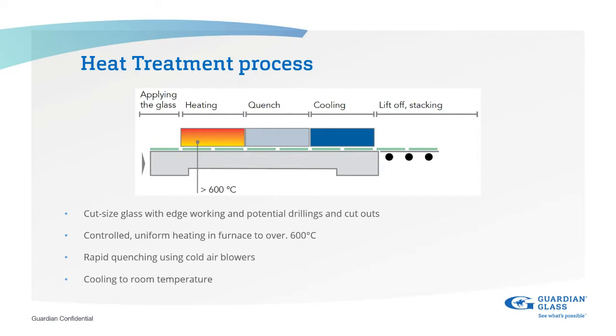Now, as you can imagine, when the glass reaches its temperature of around 630 degrees, it starts to become soft. Once the glass is up to full temperature, it will move into the quench section and the cooling section. As you can see on this drawing, we have a quench section and a cooling section. Most modern tempering furnaces have this combined now, where they will have controlled fan speeds which will give you higher pressure at the quench section, and then it will slow down for the cooling section.